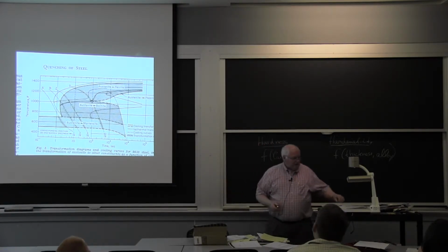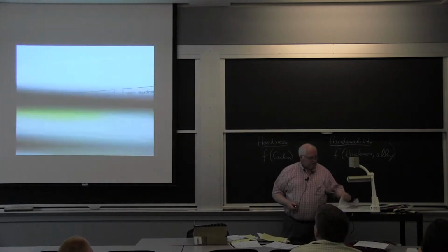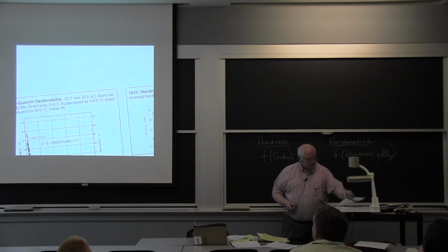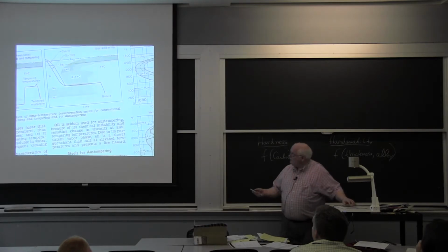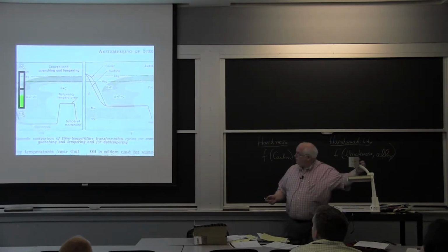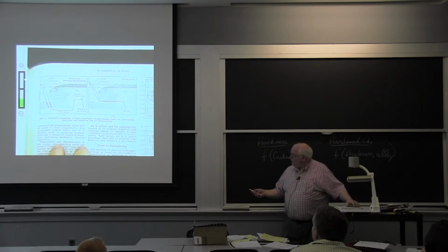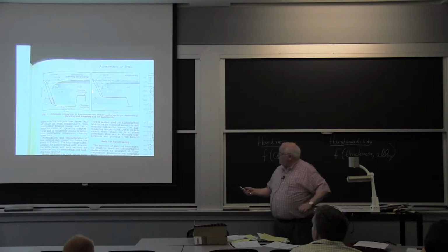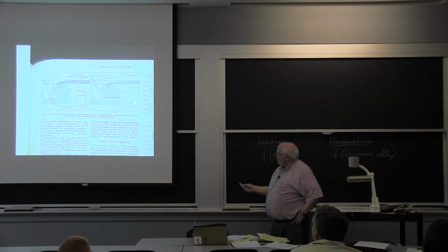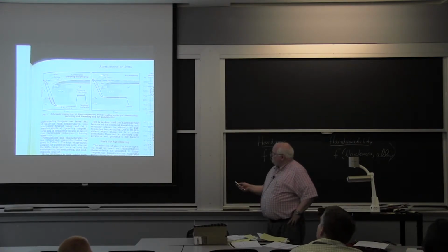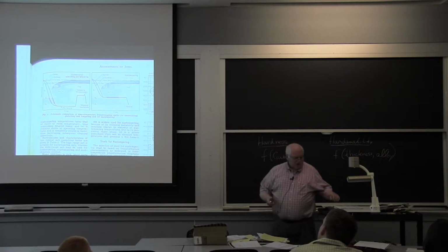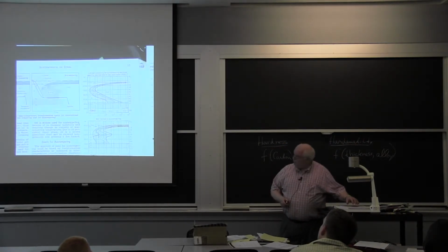So you can take these steels and you can add alloying content. Let me come down here. So here's my rapid quenching to get martensite. Here's my quenching partway. It's called austempering to get bainite. You come down at some intermediate temperature like 600 or 700 degrees, hold it there, and then you cool down the rest of the way. If you cool down slowly through this region, you get ferrite, which is a nice soft steel, easily formed.